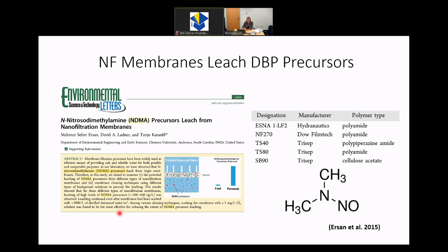This paper in particular measured NDMA. It's N-nitrosodimethylamine, which is just another one of those DBPs that I mentioned. And they found measurable levels of these leachates coming from the membrane. So the question here is, now they know something is leaching from these membranes that are used very widely, but they don't know what it is, because these methods are formation potential methods, and they're not able to tell you the identification of the precursor. They're just saying, if we react X unknown with chloramine, what will we be able to measure? They measured NDMA.